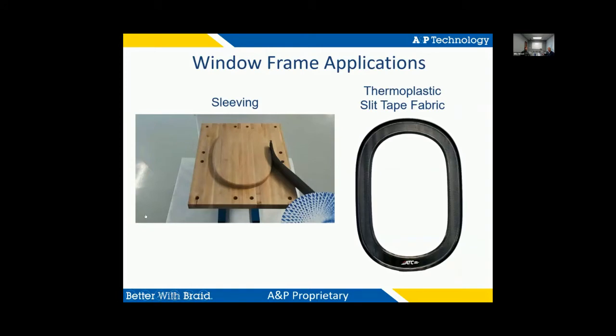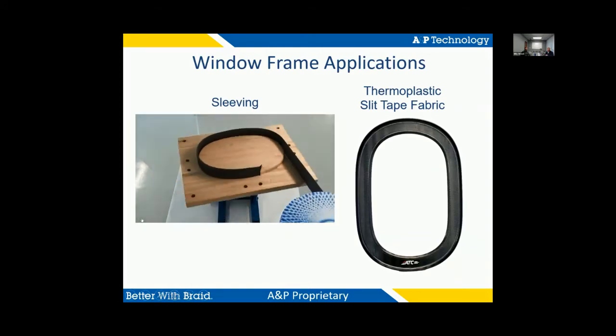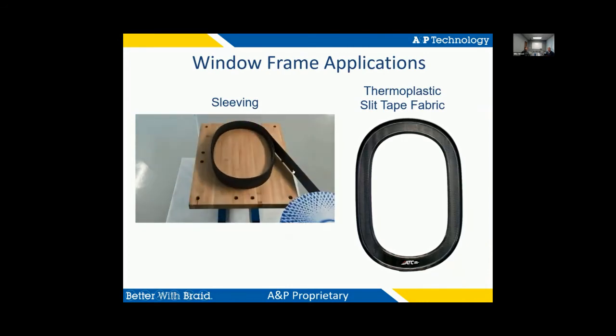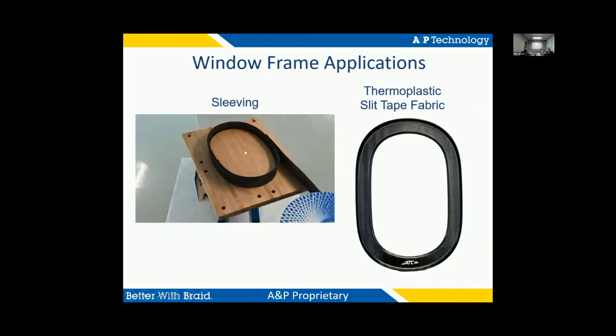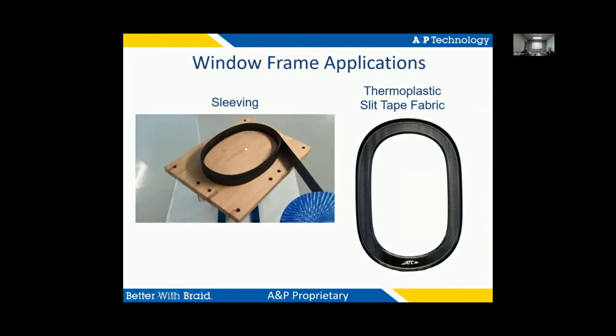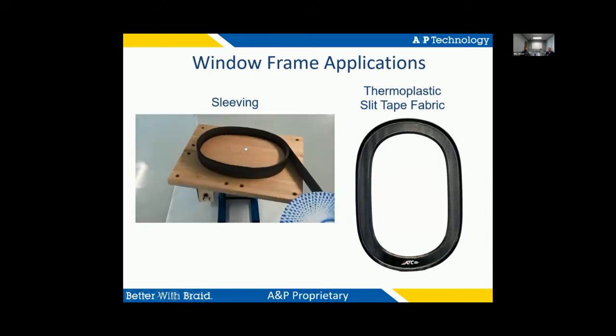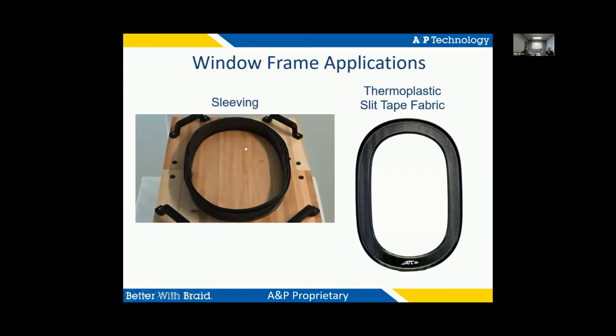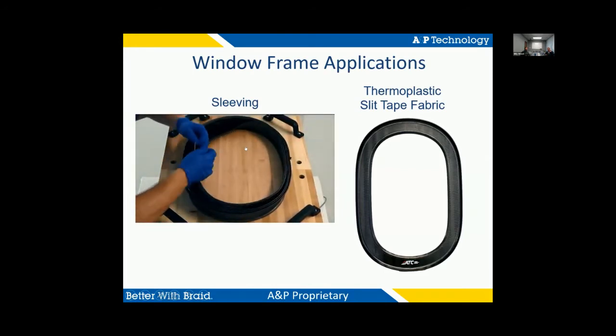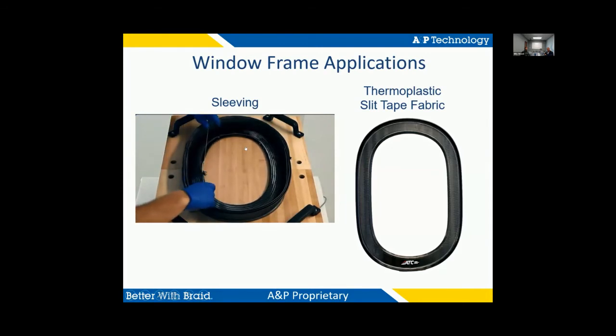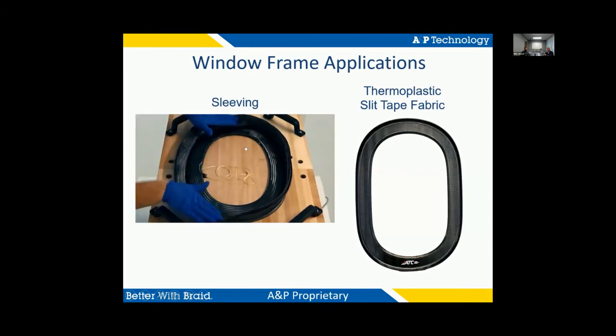Here's a great application for sleevings. So this is actually a hybrid sleeving. It's both a biax and a triax. It's triaxial here at the bottom region, biaxial at the upper region that's outside of the proud portion of the tool here. So just kind of laying that down, we're going to integrate, well, at least in this case, we introduced a drawstring yarn. We pull on that or activate that to create the downward flange, and then we can pad out the outer flange, introduce a couple noodles, and then a capture sort of surface ply, and voila, you have a window frame. As I mentioned on the previous slide, all of these braid angle changes are repeatable. And as you can see here, the layup was simple and efficient.